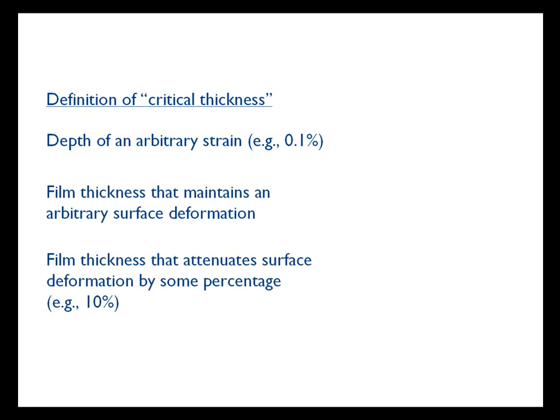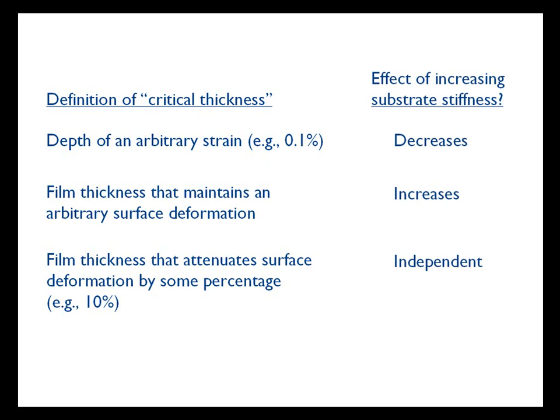Aren't these concepts all roughly equivalent? In fact, they're not. For example, these values change in different ways in response to changes in substrate stiffness. Stiffer substrates reduce the depth of strain propagation, but they require thicker films to obtain the same deformation. And the film thickness that cuts surface deformation by a certain fraction doesn't depend on substrate stiffness at all. To see why this is true, let's look closer at how these deformations are calculated.